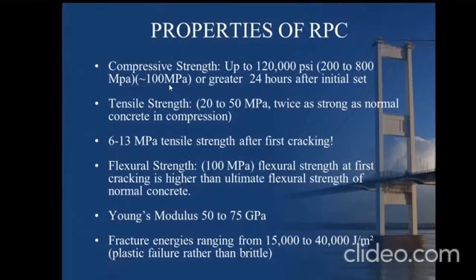And next is flexural strength. Flexural strength is also enormous. Young's modulus is great, 50 to 75 GPa. And fracture energies: generally, it requires a lot of energy in order to fracture the reactive powder concrete. You need very high capacity testing machines to test this reactive powder concrete. Your ordinary compression testing machine will not create a failure for these specimens. You need to go for very high-end testing machines in order to customize the strength and in order to finalize the mix design of this reactive powder concrete.